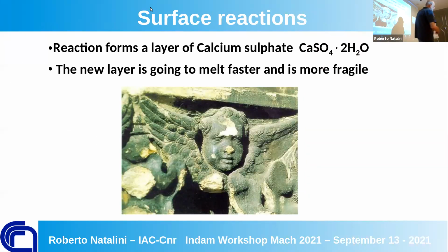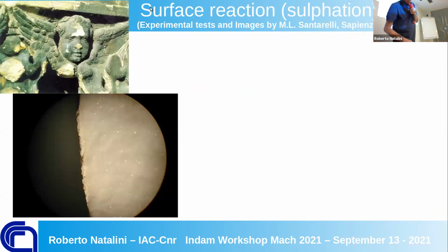And for instance, if we take just sulfation as an action, we have the reaction of SO2 with the calcium carbonate, you have production of calcium sulfate, and the new layer is going to melt faster than the marble, for instance, of travertine and so on, and it's more fragile. So, we have to study and essentially start from this one.